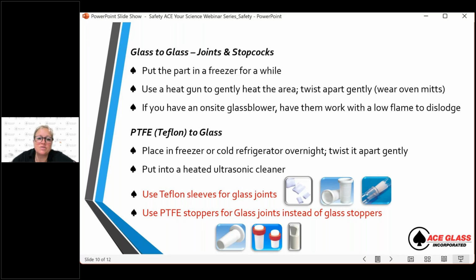Again, the easiest thing is to just put it in the freezer or refrigerator overnight and then gently twist it apart. You can use an ultrasonic bath to do that. Again, the vibration and the energy from the ultrasonic waves can help with that. Never leave glass in it too long, as it will get kind of blind. But ideally, PTFE is a lot more gentle on glass and gets it unstuck. So ideally, you would use a Teflon sleeve or a PTFE sleeve or even a PTFE stopcock to close your joints.